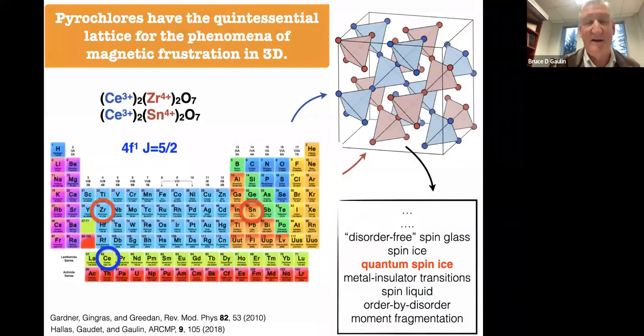But actually, we didn't initially start studying cerium stannate, and there are two reasons for that. One is that it's not easy to grow. The tin is actually very reactive. Okay, and I hope you recognize this as the periodic table. The composition of these materials is cerium 2, where cerium is in its 3+ oxidation state, and either zirconium or tin in its 4+ oxidation state, and then oxygen 7.